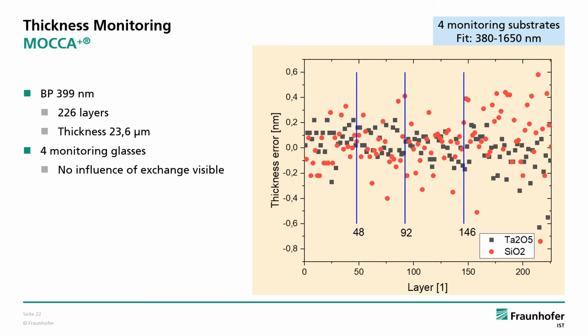As an example of the thickness errors from the single layers, I show this graph with results from the MOCCA+ monitoring. Here we see the bandpass at 399 nanometers with 4 monitoring substrates. The exchange layers are plotted as blue lines. The thickness deviations are on a very low level throughout the complete coating. Only a slight increase can be seen at the end of the last monitoring substrate that controlled 80 layers.